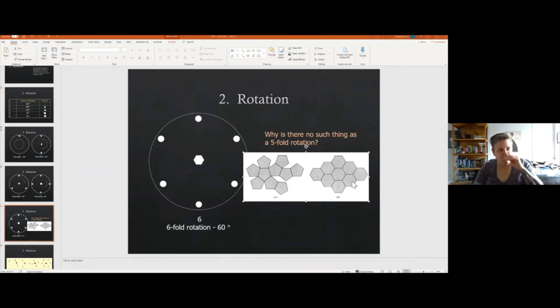So the one thing is, why is there no full five-fold rotation? A five-fold rotation does actually exist in quasi-crystals and different other things, but not common. It's because it doesn't pack well. So if you think of wanting to put atoms together so that they minimize any sort of distortions, like these empty spaces here, or they minimize the energy of the crystal, five-fold rotations don't do that. You see five-fold rotations in flowers, so it does exist in nature, but in minerals, it's not one of those things that works very well.